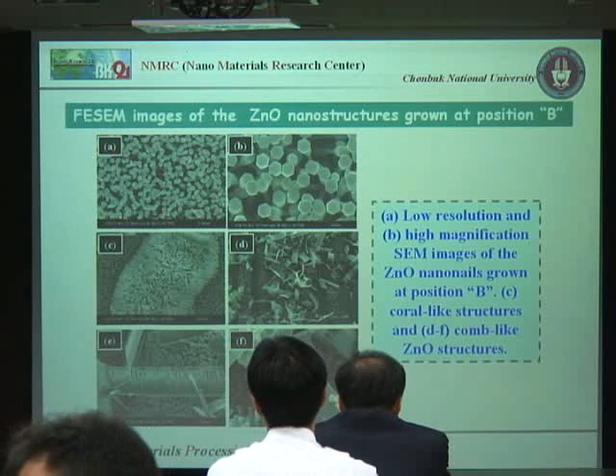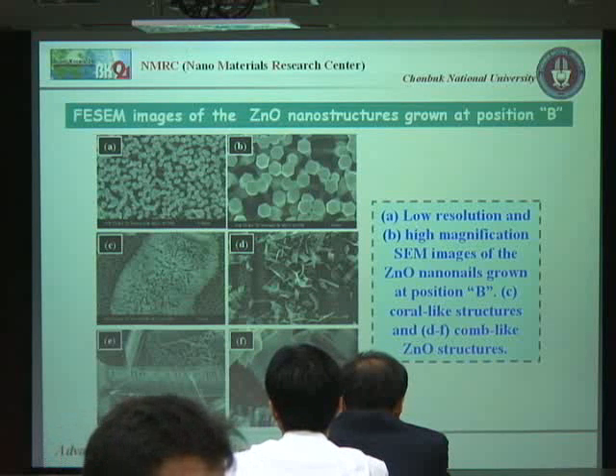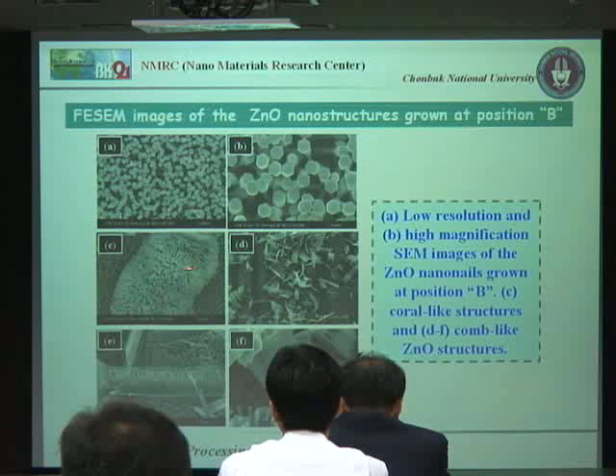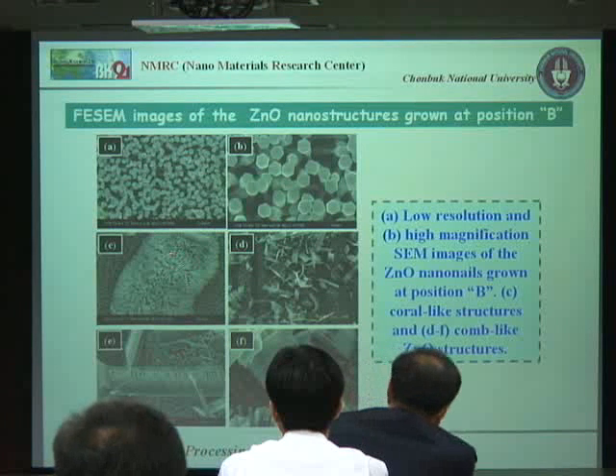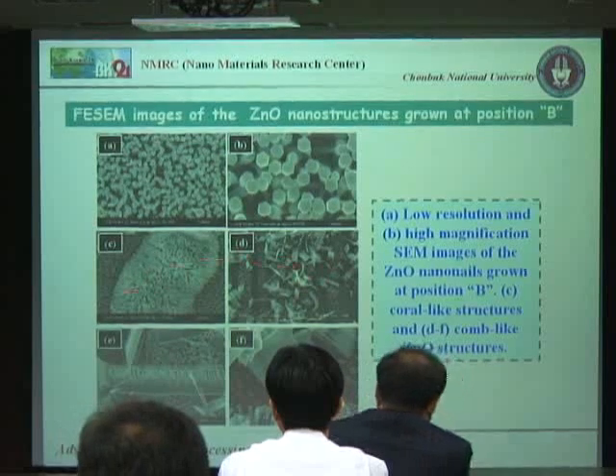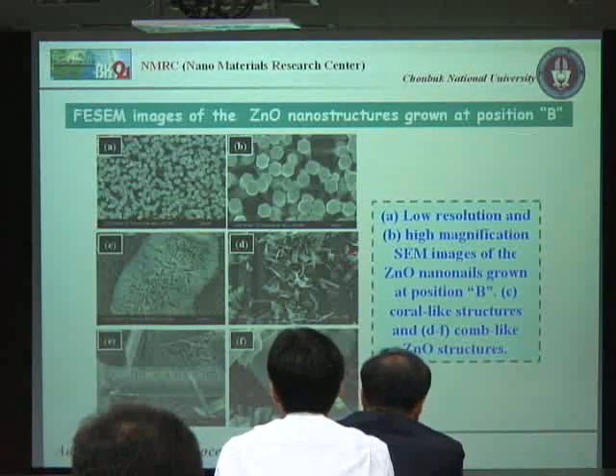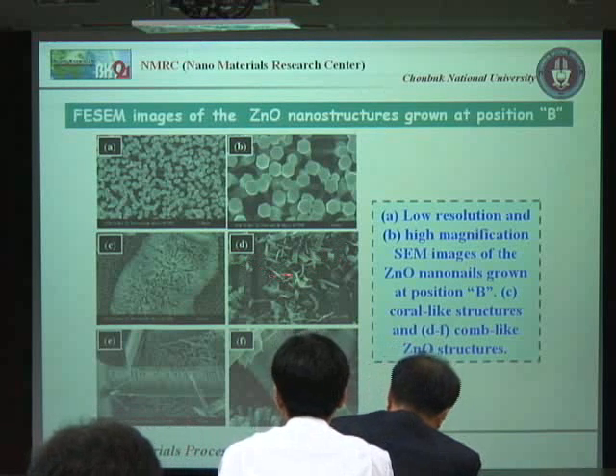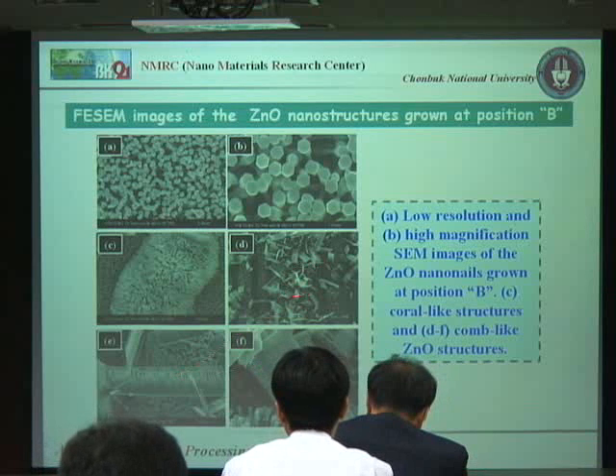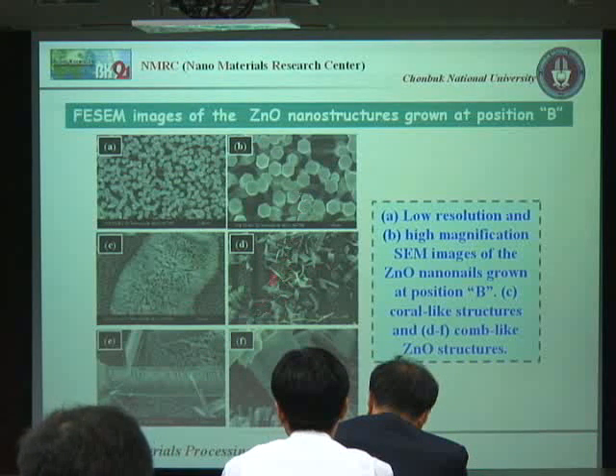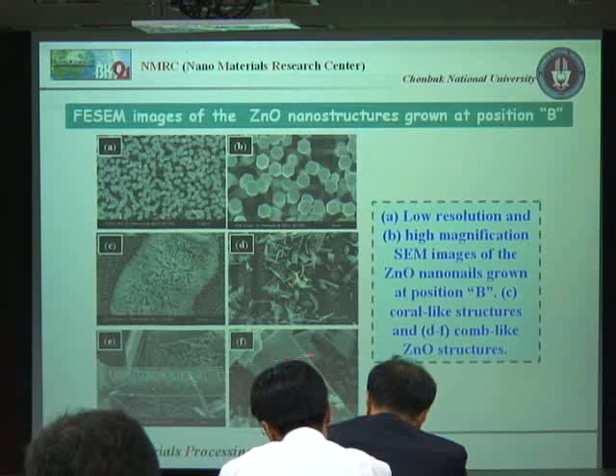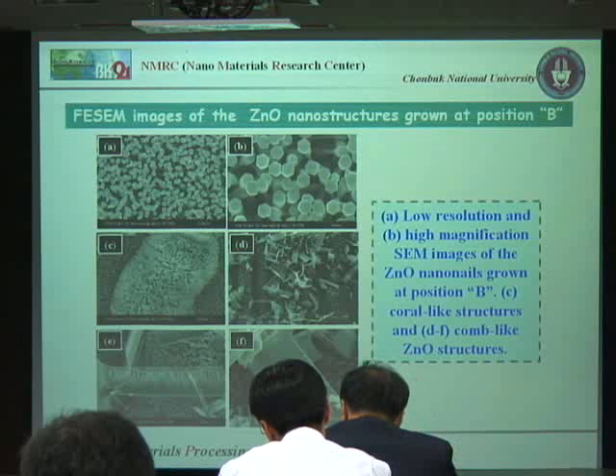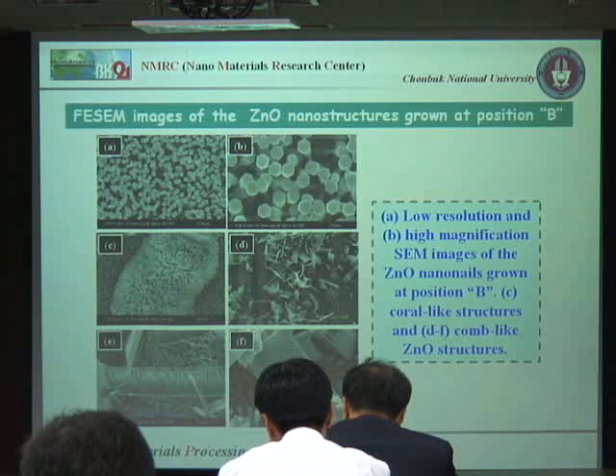Behind the formation of this coral structure, we thought that it originated because of some thickness on the upper portion of our zinc oxide nanonails, which oxidizes and grows in this form. In addition to this, at the corner portion of our substrate, we got some zinc oxide nanocombs also. These nanocombs are also made by zinc oxide nanonails. We can see clearly in this picture and this picture that the nanonails are attached parallel to the zinc oxide nanosheet at one corner and make this comb-like structure.